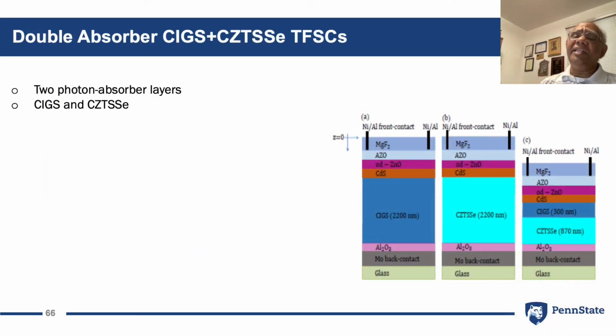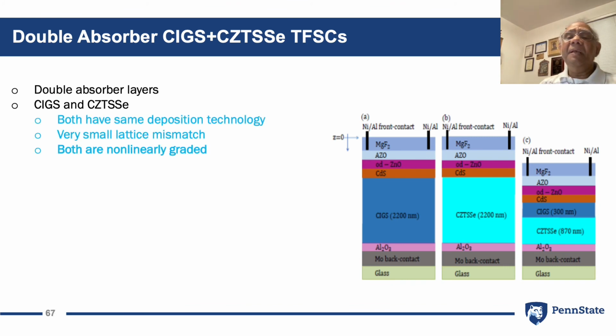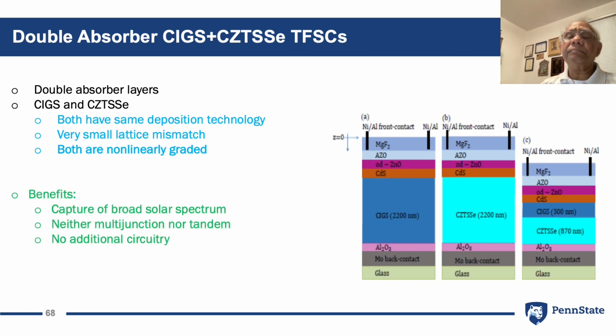Now, the CIGS and the CZTSSe solar cells differ only in the photon absorbing layer. We devised a new type of thin film solar cell in which we have both the CIGS layer and the CZT SSE layer. Both can be deposited using the same technology. The materials have a very small lattice mismatch. Both absorber layers are non-linearly graded in this new type of solar cells. This way, a larger portion of the solar spectrum can be captured without the need for additional circuitry used in multi-junction and tandem solar cells.